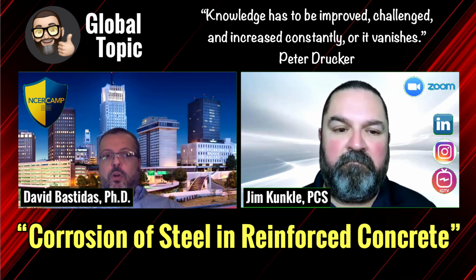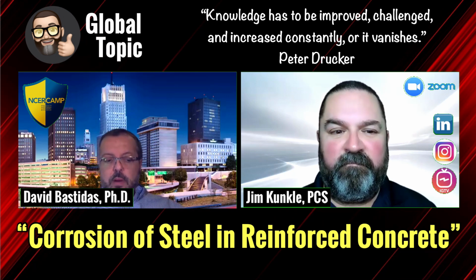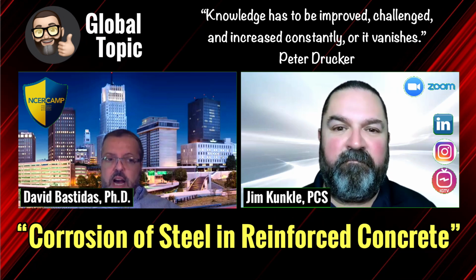All right. So once corrosion starts, there is the passivity breakdown and then the further propagation. What is the reason for that? The reason is that the oxides and iron oxohydroxides exert a high pressure. The recrystallization pressure of these oxohydroxides produces expansion forces. Thus, what we suffer in reinforced concrete is a loss of adhesion, delamination, spalling, cracking, and then further ingress because of the cracks. It is easy for the external agents to get in. So it's kind of an autocatalytic problem.